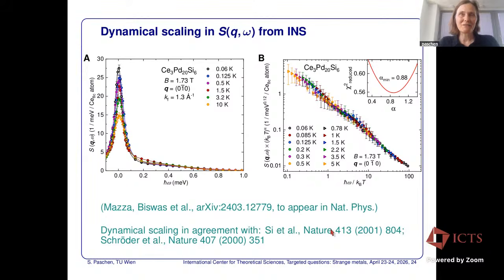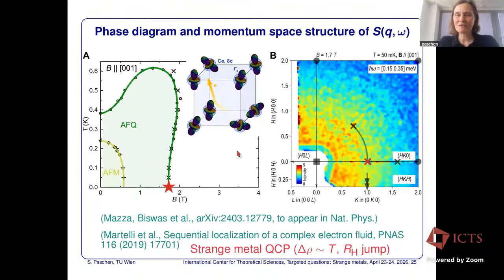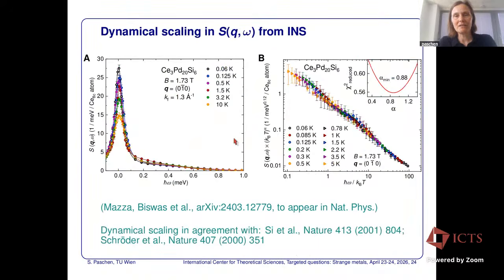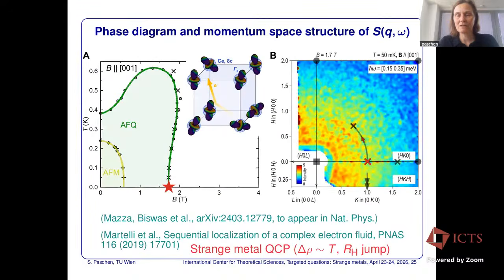So one thing that we did very recently is, I just wanted to show you this momentum space structure because we also discussed it yesterday. So that's really the typical situation we have at least in this compound and also in other heavy fermion systems where this local or Kondo destruction quantum criticality is seen, that this very low energy response, it's integrated from 0.15 to 0.35 millielectron volt, is really broad in momentum space. And the data that we show here are picked far away from any ordering wave vector and, of course, also from any Bragg peak. So we just go in the places where usually there would be nothing.